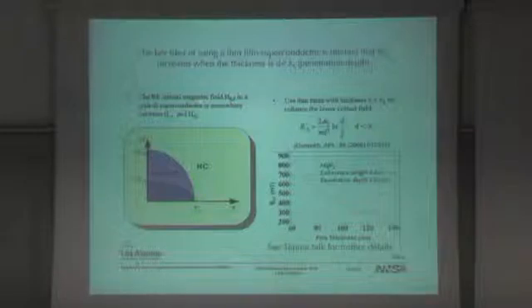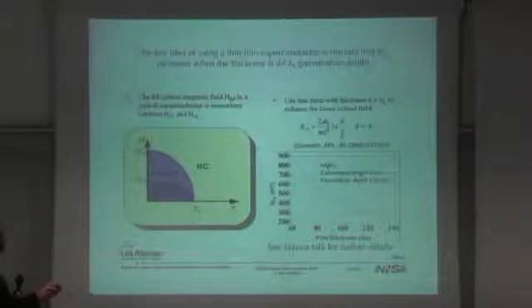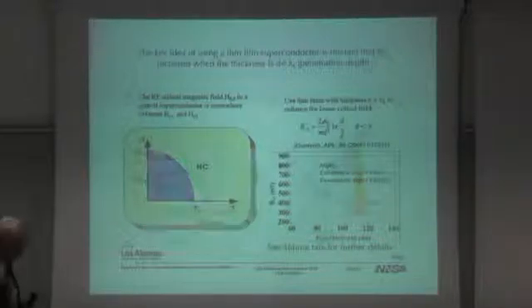In fact, the critical magnetic field that we're concerned with, where you would obviously see quench, is somewhere between HC1 and HC2, and if we can't get at that directly, at the very least, as Claire pointed out, a figure of merit, if we stay below that, is HC1 that allows us to stay below the HRF. In this particular calculation, this is for MgB2. These are the values we're using in the calculation: five nanometer coherence length, penetration depth of 140 nanometers. You see that as the film thickness gets lower, the critical field HC1 goes way up. And Tsuyoshi will talk about this slide and the next one in much more detail.